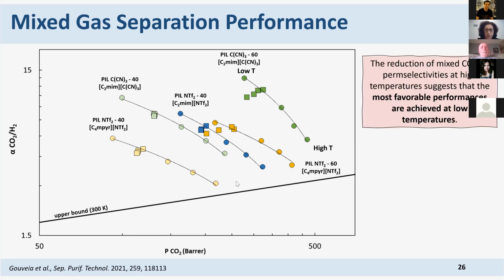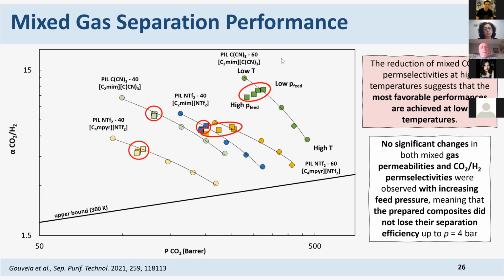Realize also that when I change temperature, the difference in temperature greatly reduces the efficiency of the membrane in terms of selectivity and also in terms of permeation. And this happens for all membranes. And in what concerns pressure, pressure does not have much effect on the permeation properties of these membranes. So this is good news.